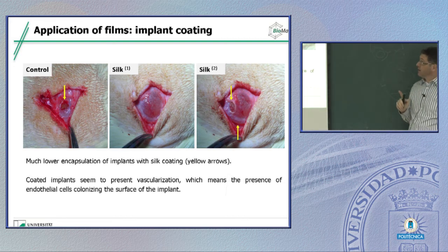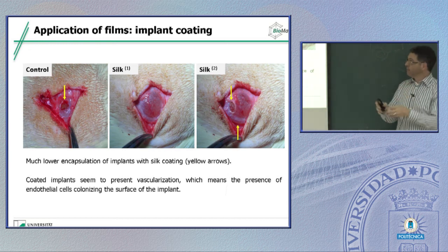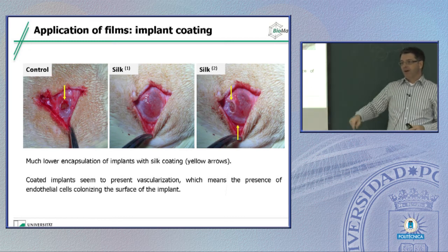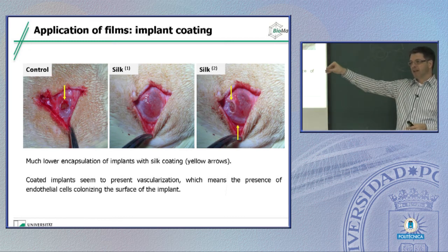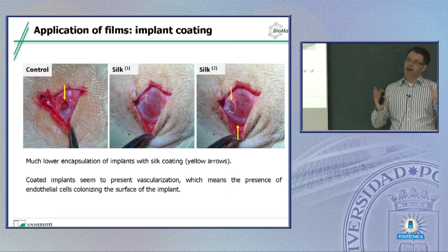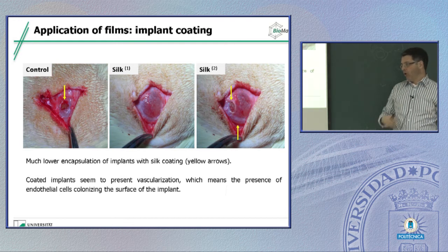But this was only the one interesting thing. There was another interesting thing, and this was really intriguing, and we didn't think about that to begin with. Has any one of you ever seen a silicone implant or held it in the hand? Probably not. Well, I didn't either before we started that. But we got the implants, and we just unpacked them and put them on the shelf. And after a few days, they're getting slippery, slimy. Why? They're not tight. So there's always unbound silicone oil that actually moves through that silicone membrane all the time,